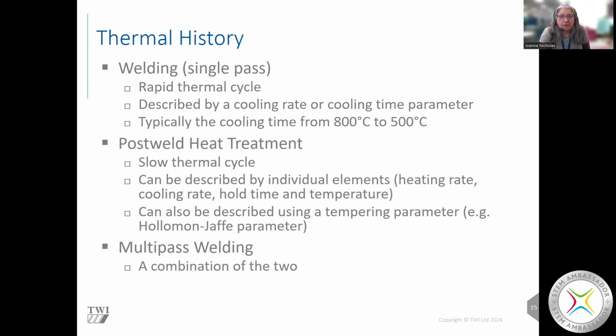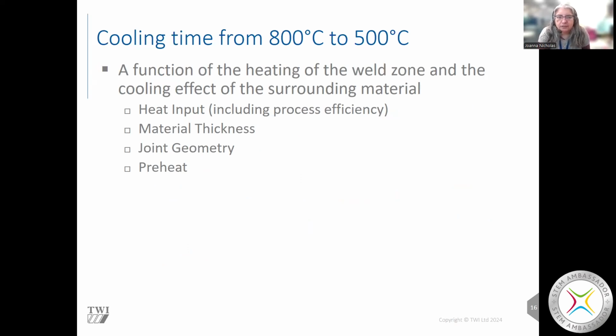And when we're thinking about multi-pass welding, where we're putting down more than one weld bead to fill up a joint, then we're using a combination of those two methods to describe the thermal history that we've experienced. So this cooling time from 800 to 500 depends on the thickness of the weld material that we're going to be putting down, how much heat is going into the material. That's called the heat input.